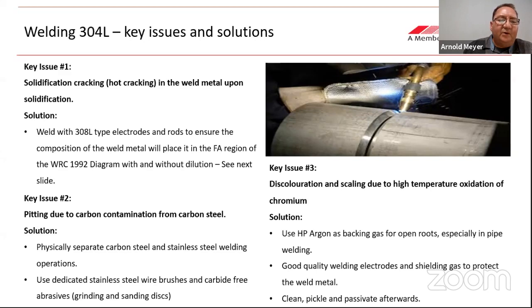The pitting due to carbon contamination, very important in any stainless steel welding, is solved by physically separating carbon steel and stainless steel welding operations from each other, and using dedicated stainless steel brushes and carbide-free abrasives. Whenever your stainless steel is hit by grinding sparks from carbon steel, a pit will form there. Because of sensitization, the carbon reacts with the chromium, they form chromium carbides, and because of that, locally on that spot, the chromium will be depleted in the stainless steel and pitting will occur.